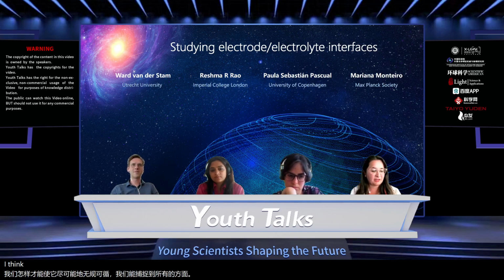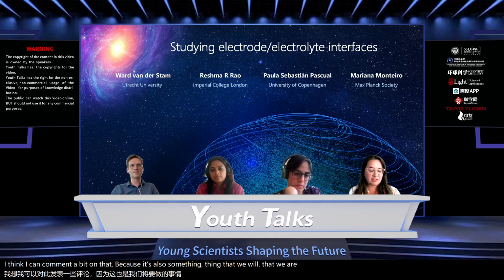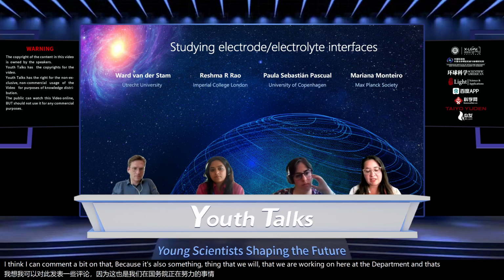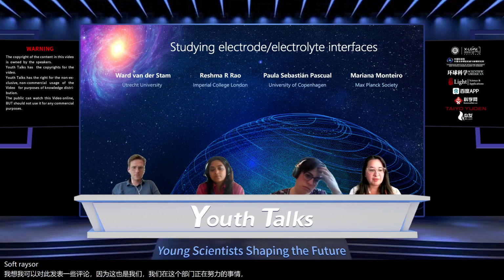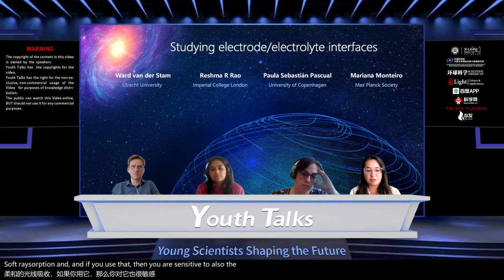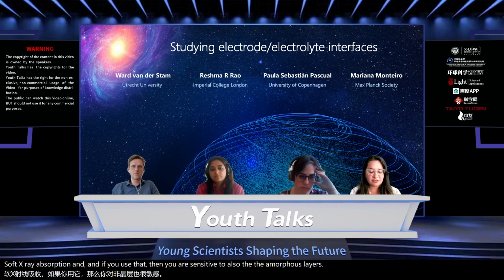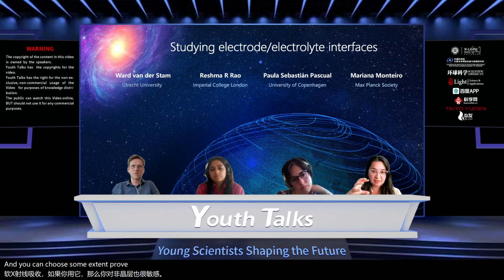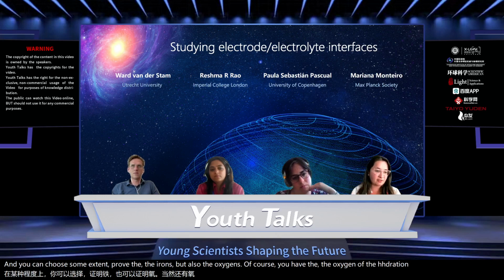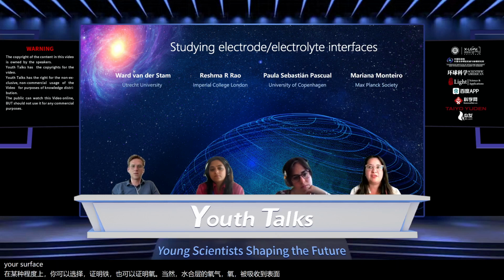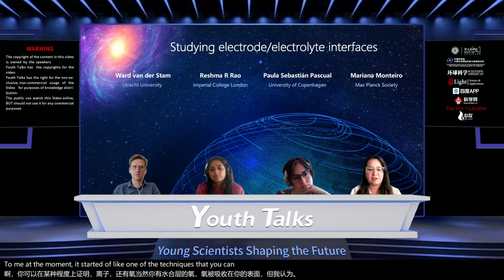I think I can comment a bit on that, because it's also something that we are working on here at the department, and that's soft X-ray absorption. If you use that, then you are sensitive to the amorphous layers too, and you can to some extent probe the ions, but also the oxygen, of course the oxygen of the hydration shell and oxygen adsorbed on your surface. To me, at the moment, it's one of the techniques with which you can get the most out of these interfaces.